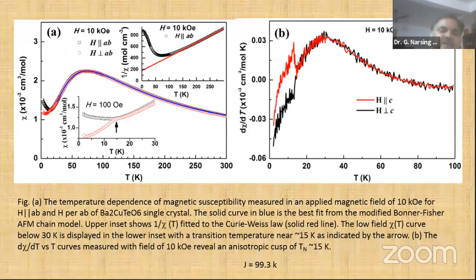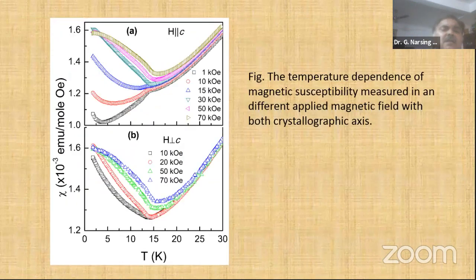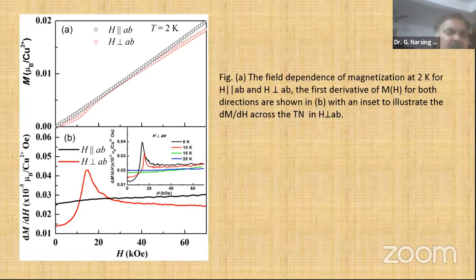If it were in all directions, then you would get a very nice lambda maxima in heat capacity. This is different with a different magnetization. You can see H is perpendicular to C, so it's only going up, but parallel to C, initially it is going down and suddenly it is flipping. So they call it a spin flip transition around 15K, at a magnetic field of 15 kilo oersted. This sample exhibits a spin flip transition, which we can see in a hysteresis curve. You can see here around 2K, around 15, there is a change. This change we call a spin flip transition.